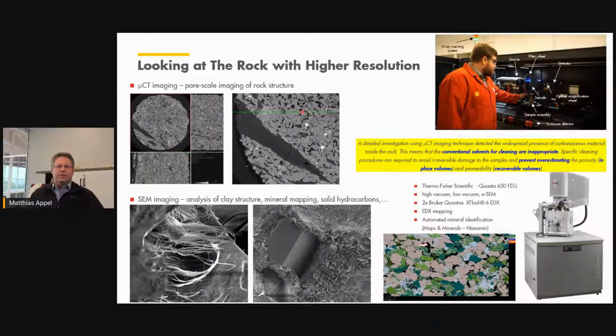That allows us to get a resolution of maybe a micrometer, and a micrometer is good enough to see individual pore structures. For instance, here you see on a sample the clear difference between the normal pore structure comprised of grains and pores, but also a large fraction of what's called carbonaceous material. So basically organic fragments have remained in that rock, in that reservoir. And by looking at the pore structure with that resolution, you see that one needs to be very careful how to treat that plug, for instance, in the initial cleaning process. When exposing carbon-like material to methanol, for instance, the methanol creates fractures in the carbonaceous material. And these fractures will have a very strong contribution to permeability, potentially even affecting porosity. So that would affect in-place volumes that are calculated and permeability in terms of recoverable volumes.